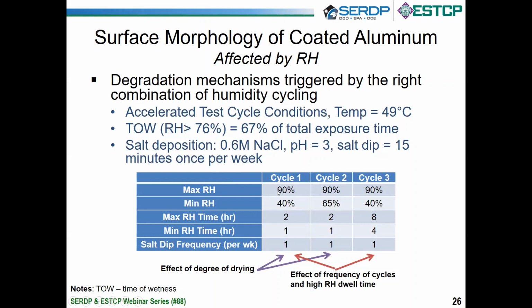So let me point out a couple important facts here. In this first cycle, you can see that we're at 90% relative humidity, and we dropped that relative humidity down to 40%. So this is a two-step cycle. We hold that at 90 for 2 hours and dry it for an hour. In the second cycle, we have the same wetting and drying time, but instead of drying it, we drop the relative humidity only to 65, so that sub-deliquescence point. But we know corrosion is still occurring.